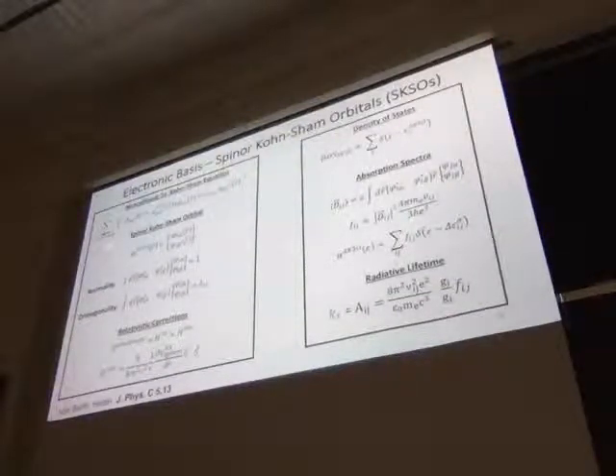We have to use non-collinear DFT, and I'll explain that in a second. Basically, this equation sums over spin states for the materials, and in some materials you get spin mixing, so spin is not a good quantum number anymore. The solutions to this non-collinear one-electron equation are spinor orbitals, a two-component vector made up of spin alpha and spin beta, spin up and spin down components. And they obey the usual rules you expect for good orbitals, normality and orthogonality.